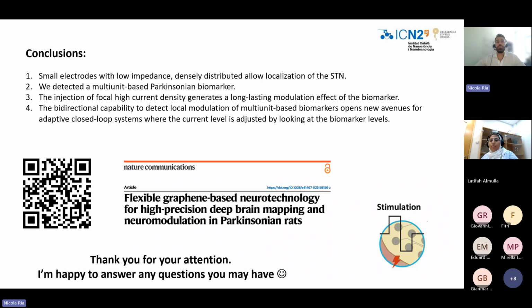PEDOT is also a competitive material with very good performance, so high charge injection and low impedance. Graphene oxide is a good alternative. It's a low-cost material. It's flexible, it is biocompatible, and we proved also that it has a very good stability. So it allows the implant to work chronically for months or years. Specifically about the advantages for this specific application, it's difficult to answer, but we think that graphene oxide can be a good alternative to other high-performing materials available at the moment used in the research field.